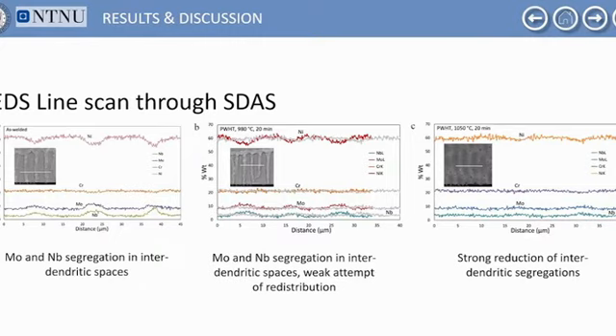This is the distribution of the element in the as welded joint. By moving to the post-welded heat-treated joint at 980 degrees, we observe that we have little reduction of such kind of segregation. So we have a partial redistribution. And by moving to the samples heat-treated at 1050 degrees, we observe a homogeneous distribution of the key elements.